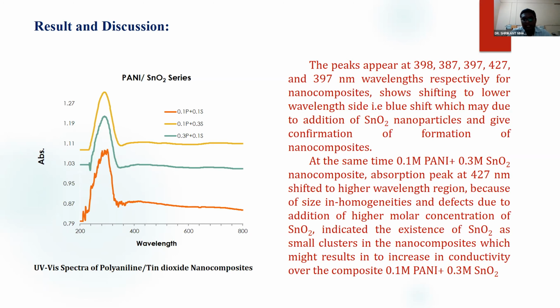Due to that shifting, I can conclude that there is a formation of nanocomposites of polyaniline and tin oxide. At the same time, I am making different solutions by changing the molar concentration of the polyaniline and the SnO2. I observed that the absorption peak at 427 nanometer is shifted toward the higher wavelength, and it may be because of the addition of a higher molar concentration of SnO2. That indicates there is an existence of clusters of SnO2 material in that nanocomposite, which might increase the conductivity of that nanocomposite of 0.1 molar polyaniline plus 0.3 molar of SnO2.